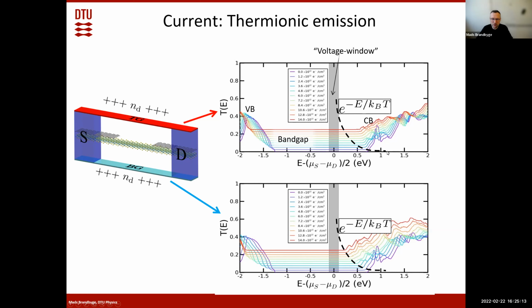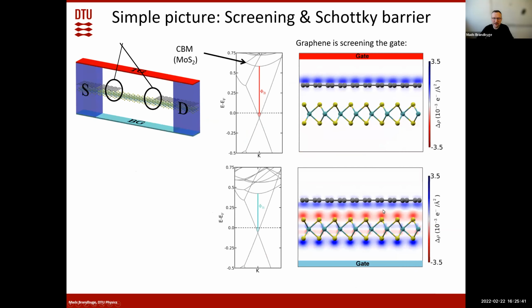So it's the conduction bands which conduct in this device. You can see that when we do the top gating, the conduction band is just moving slowly towards the voltage window, so slowly down this exponential curve. Not turning on too much, but we have a different behavior when we do the back gate. Here it's moving much more rapidly towards the voltage window, and we turn on the current much more rapidly. The reason for this is, in the end, once we've done all the complicated calculation, pretty simple. It turns out that this device is controlled by the Schottky barrier between the graphene electrode and the MoS2. That is the main working principle of this device. What happens when we gate it is that we shift the conduction bands towards the Fermi level of the device. So it's this Schottky barrier which controls everything.